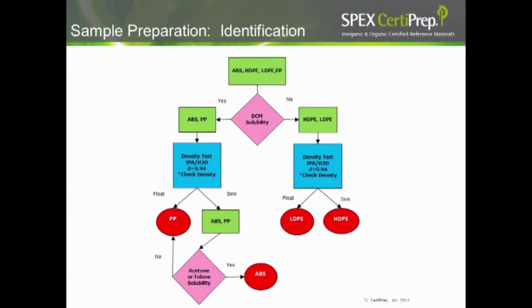From that point, when we took those plastics and tried some solubility tests, such as in DCM, that was able to divide out the polyethylenes, which are very insoluble in almost all solvents, from something like an ABS or a polypropylene, which was soluble in DCM. Then we did more density checks to find out if it was a low density or a high density polyethylene, or if it was a polypropylene or an ABS plastic.